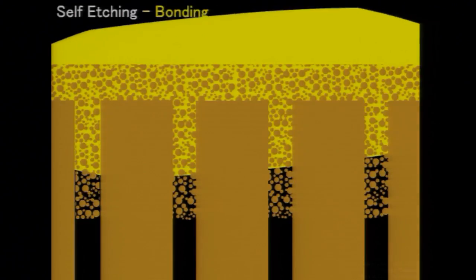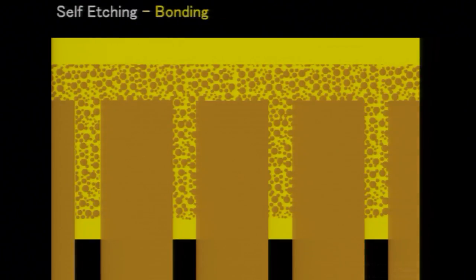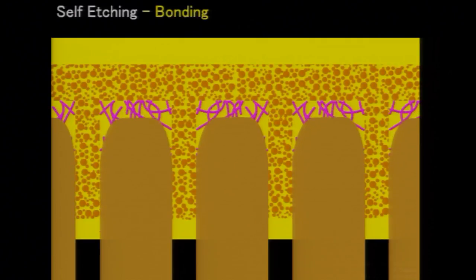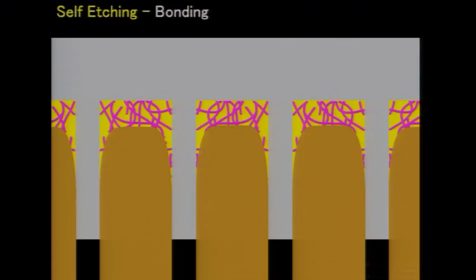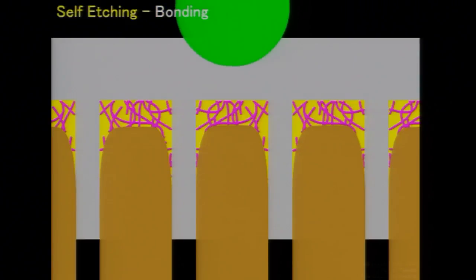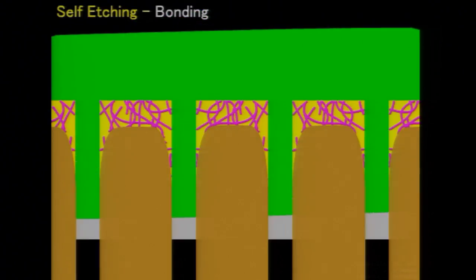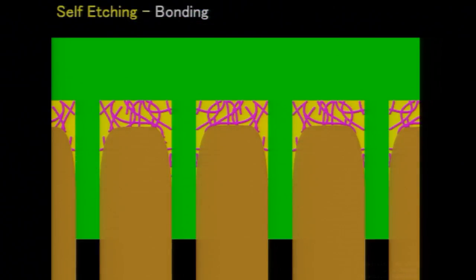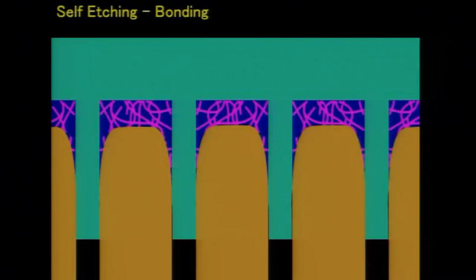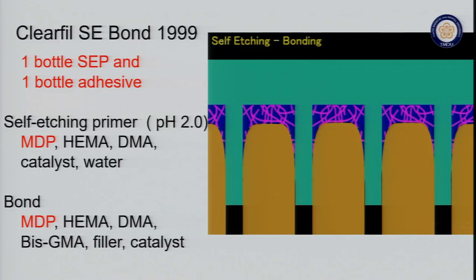The self-etching primer is strong enough to remove most of the smear layer, and the very superficial layer of dentin is demineralized. And this collagen is already treated with adhesive resin monomers. That's why it does not shrink at all. Then we apply the bonding resin. The bonding resin can penetrate into this demineralized layer very well, and we can cure. And in the hybrid layer at the interface, there is no weak point in this case.